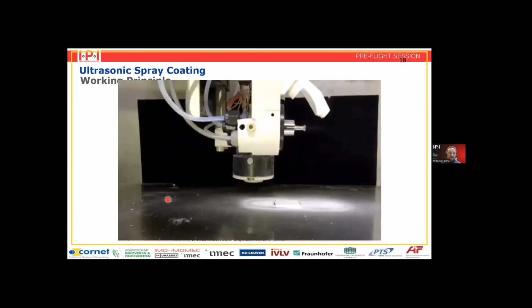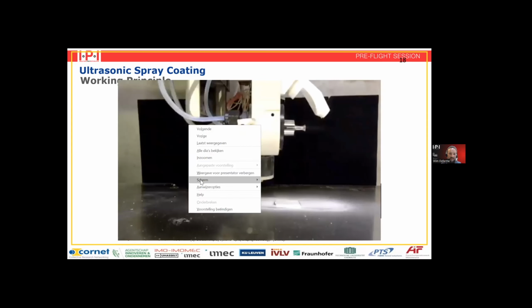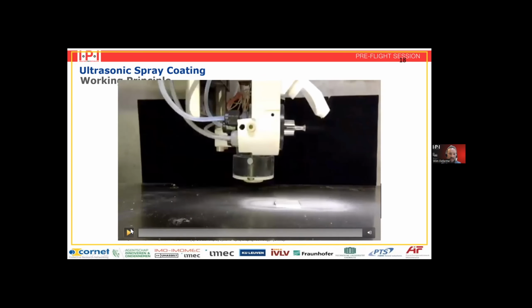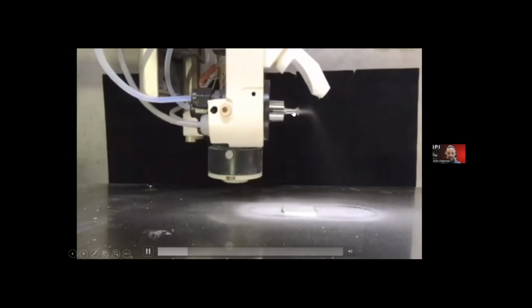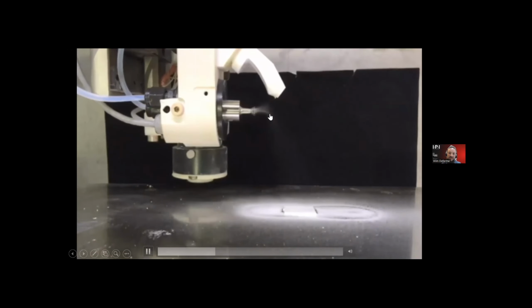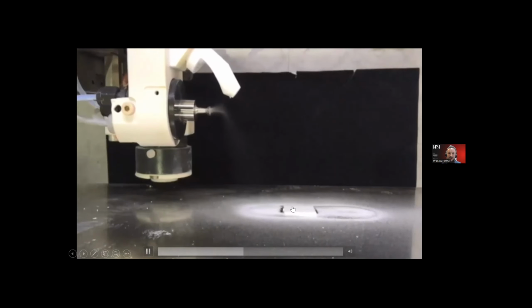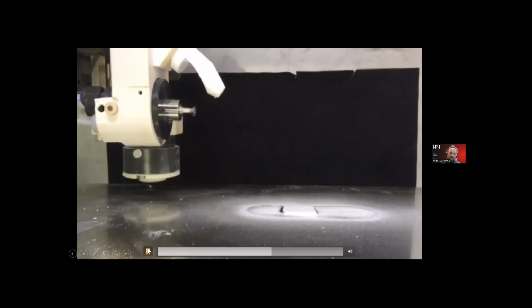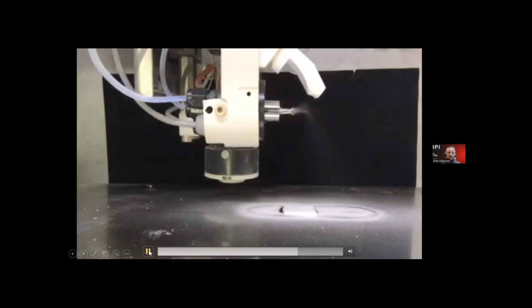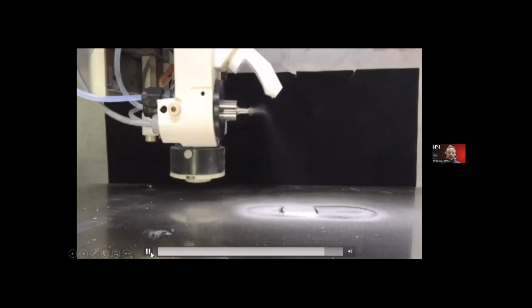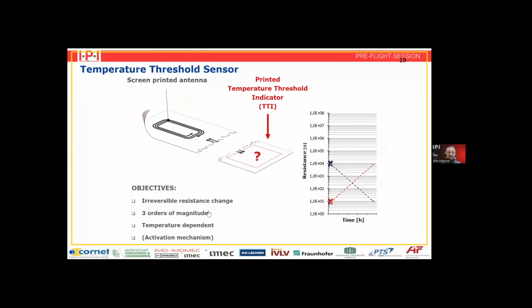Here you see a small video of the system itself. Let me try to show it. Here you can see the nozzle, you see the shroud gas, and here you see the droplets that are brought towards the substrate and sprayed onto the substrate. And for this application, the coating thickness was not really that crucial, but if we look in organic electronics, something we also do, we need coatings that are around 30 to 40 nanometers, and then this ultrasonic spray coater can do the job in depositing these ultra thin coatings.